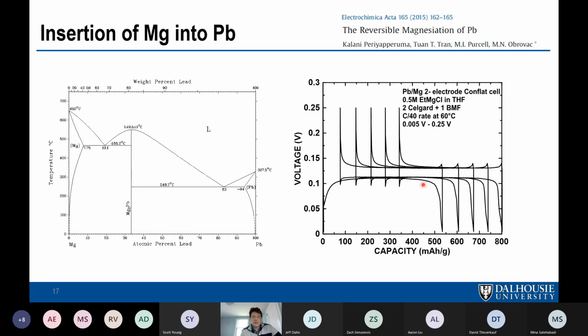And this slide just illustrates that, even though the plot on the previous page was just made from the ICSD database, you can insert these other atoms, even doubly charged ions like magnesium, into alloys, and you can do it reversibly. So it's possible to do this kind of chemistry with other elements than lithium.